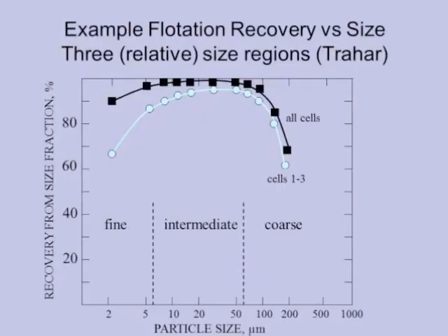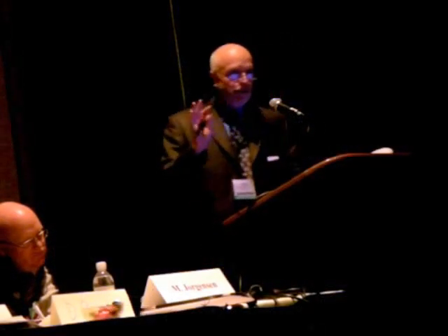And this is just an example of many that we all know, that the performance of a flotation circuit and many other mineral separation processes is very sensitive to particle size. And the more material we can squeeze in the high recovery region, the overall increase in efficiency, the overall increase in metal recovery we're going to achieve. Okay, so that was the first case study.